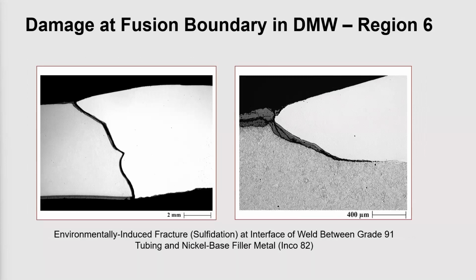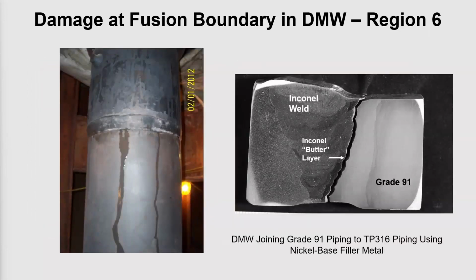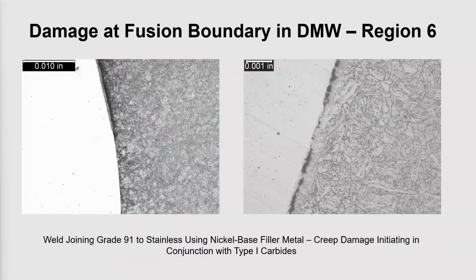There have been occasions where environmentally driven cracking has formed right along the fusion boundary in the base metal, in the grade 91 base metal. And then this is an example of damage in a dissimilar metal weld, grade 91 to type 316 piping, where nickel-based filler metal was used. And you can see here the creep damage forming right along the fusion boundary.